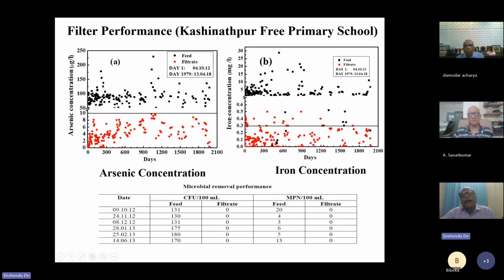Then the iron concentration is sometimes very high. It changes from 1 ppm, which is 1 milligram per liter, to 30 milligram per liter. The acceptable limit for iron is 0.3 milligram per liter, and the filtrate is mostly below 0.3 milligram per liter. Looking at the microbial removal performance, the WHO limit is that there should be no bacteria present in drinking water. Although various filters claim 99.9% removal, some finite amount of microbes still remains in the final filtrate. But in our case, we found that the bacteria concentration in the filtrate is below detection level.